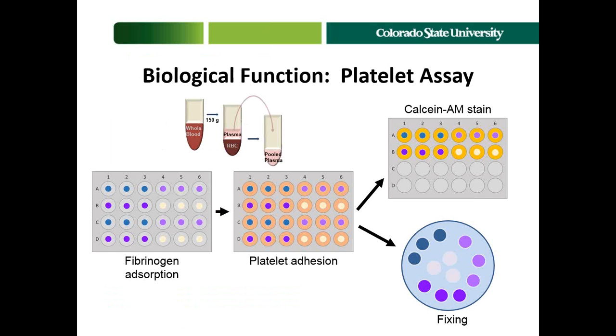So we actually have a platelet assay test where we can pool plasma, look at relative fibrinogen absorption, platelet adhesion, as well as cell viability in a microtiter plate assay, and compare that both to our control as well as our active surfaces, and can demonstrate then that in our case all of the platelets remain at least reversibly active, even if they're knocked out for a short period of time at the interface of the material.